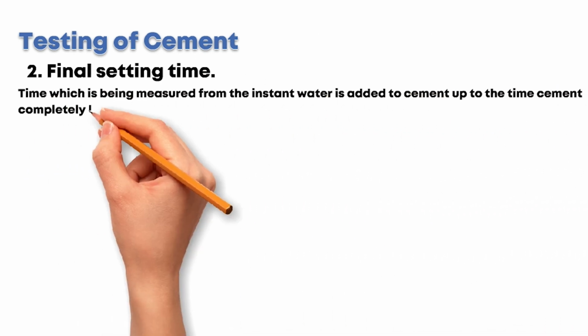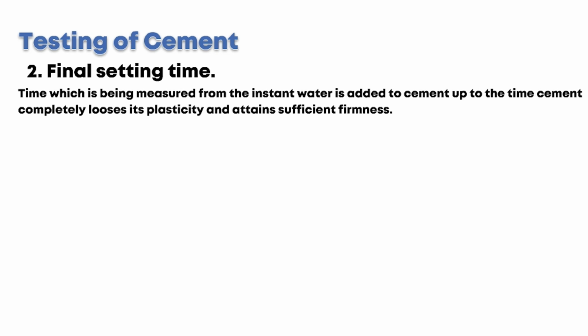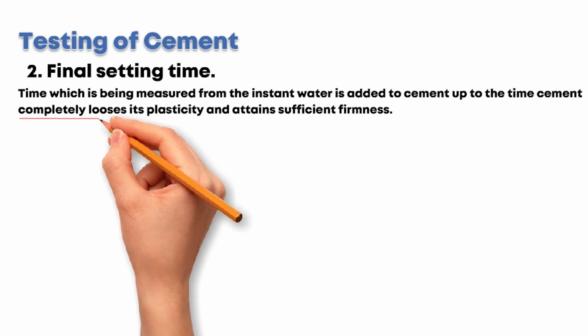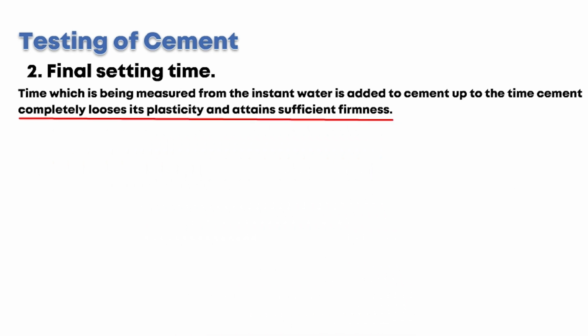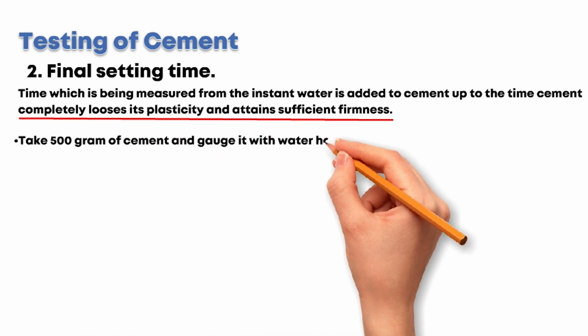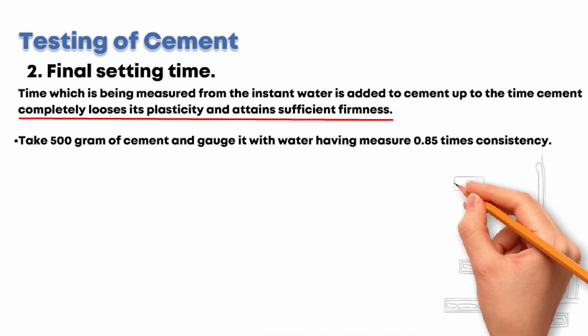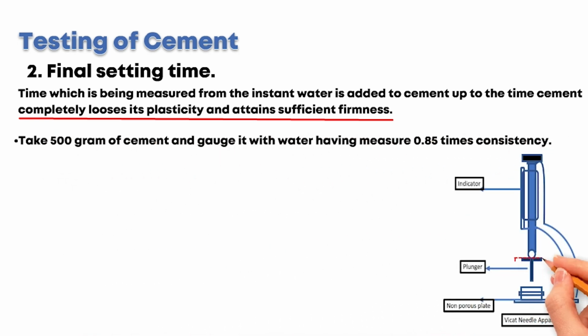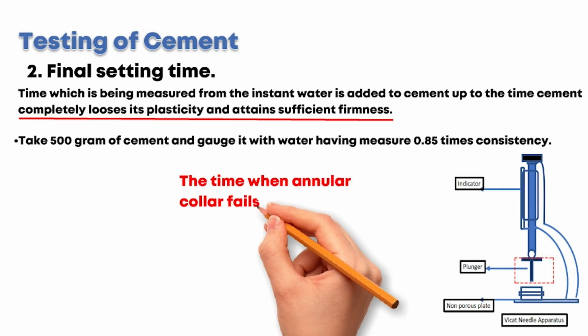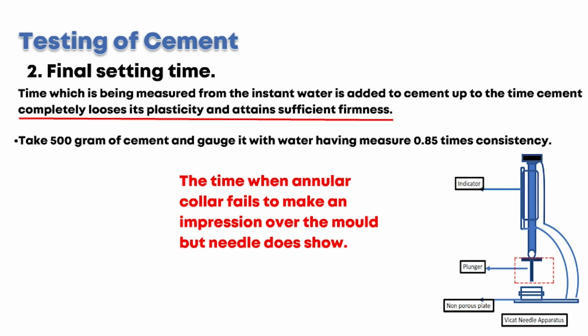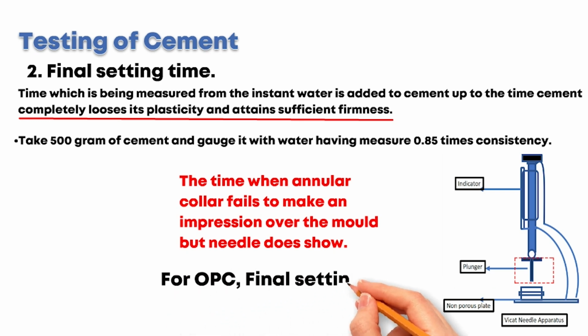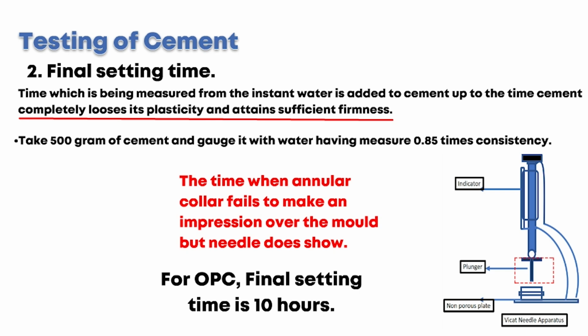Final setting time is the time measured from the instant water is added to cement up to the time cement completely loses its plasticity and attains sufficient firmness. Take 500 g cement and gauge it with 0.85 times consistency. Lower the annular collar with needle gently and release it quickly. Final setting time is the time when the annular collar fails to make an impression over the mold, but the needle does show. For ordinary Portland cement, final setting time is 10 hours.